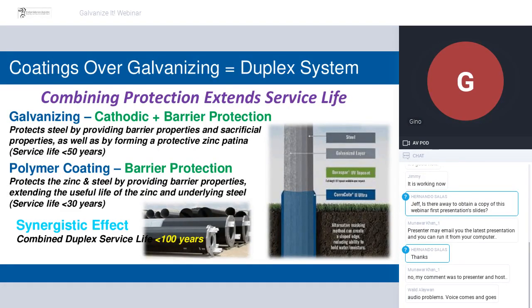And the barrier protection simply stops or greatly reduces the ability of the electrolyte to get in contact with the steel so that the corrosion cell and circuit cannot form. So the polymer coating protects the zinc, which preserves it. And then with the passage of time, depending on what the service conditions are, and you can see in the image here to the right, that you do have a portion of the coated pole protruding from the